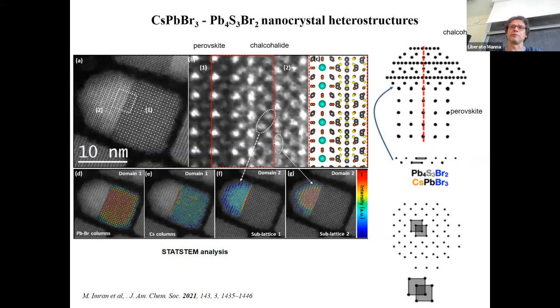Well, first of all, with Sara Bals, we did advanced STEM analysis on these nanocrystals. We also did a lot of quantitative analysis. Sara has been showing some of this. We were able to demonstrate very nicely the epitaxial relationship between the perovskite domain and the chalcohalide domain. We could even identify the continuation of the lead cation sublattice going from the perovskite to the chalcohalide domain. And what you see in this image, maybe it's summarized more easily here.